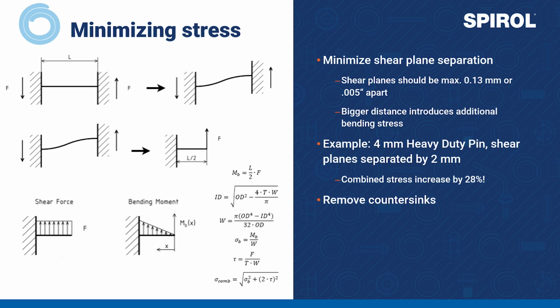Now, you may think that if someone is going to have a 2 millimeter clearance between their hub and shaft, that's not possible, and you would be right. But if there is a 1 millimeter countersink on each side of the hole, that creates essentially the same effect. Countersinks should be removed from wherever shear occurs.